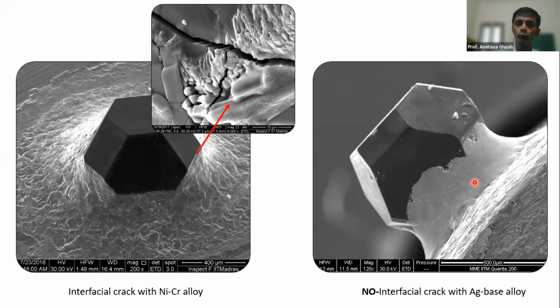And when we used a silver-based active alloy with the presence of titanium as an active element, we saw that there is absolutely no crack at the interface. So this major problem, which is industrially found, could be resolved. Now there is another issue I must share with you. See, we are using a silver-based alloy, and this silver-based alloy is quite soft. That is why it can withstand that stress, and it is not allowing any crack to initiate.